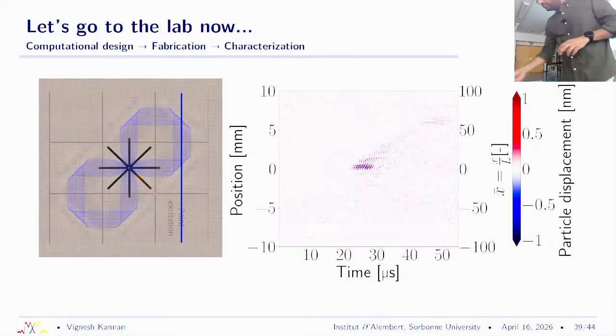It's a very nice question, but above the holes, the black stars, the rods are standing by themselves, but above the gray area, are they linked to the base? No, they're not linked. They're completely freestanding. The holes are basically to do the excitation of the beam, but you have a 2 to 3 micron region throughout the entire surface, which is freestanding. So we know that they're not in contact with the base layer.